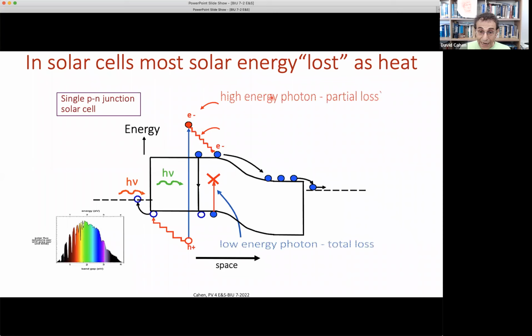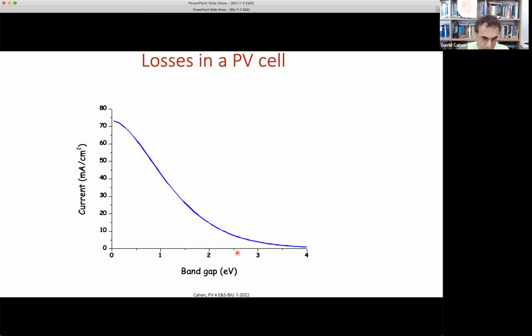So high energy photons, partial loss; low energy photons, total loss. These are the two most important losses in a solar cell. That gets you already very quickly to 40%. And the rest I'll give you now. So this curve is as a function of the photon energy, and in this case, the band gap. In other words, the minimum energy that the cell can use to take an electron from the valence to the conduction band and therefore activate the photovoltaic effect.